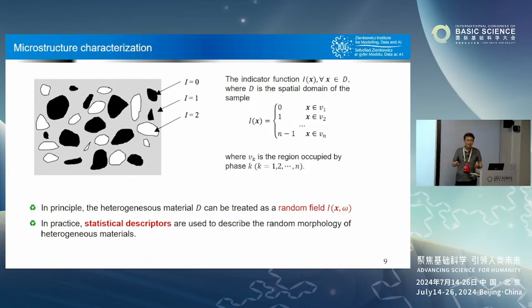So how do we quantify this random field? This is a 100 by 100 pixel image. So you would have 10,000 random variables here. That random field, just in 2D, exceeds much of your mathematical capacity, unless you start to introduce a simplification. If the whole field is Gaussian, then you only need two parameters. But that's very rough, very brutal. Material is not Gaussian, for a fact.